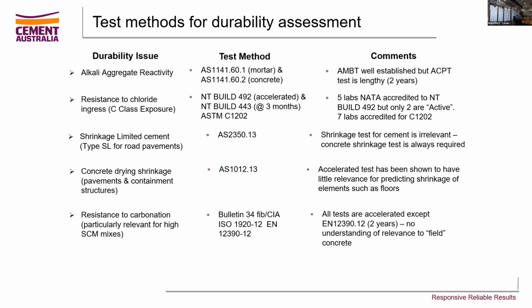Okay, another quite a topical subject at the moment is the resistance of concrete to carbonation. Now, why is this a problem? Because there is a school of thought that says that concrete mixes with higher levels of supplementary cementitious materials, i.e. low carbon concrete mixes, are more prone to carbonation over a period of time. Now, the problem here is there are 3 test methods, the FIB method, the ISO method, and the EN method, 2 of which are accelerated methods.